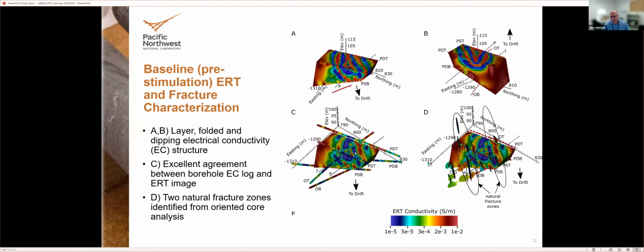In resistivity, things match very well. And then very importantly, I've superimposed here where the natural fracture zones are. These were identified through oriented cores that we took from each of these wells. And there were 2 very prominent and well-developed fracture zones. And this one in particular on the right is very important, as you'll see for the experiments that we conducted.